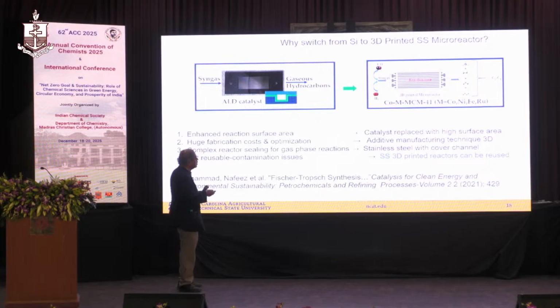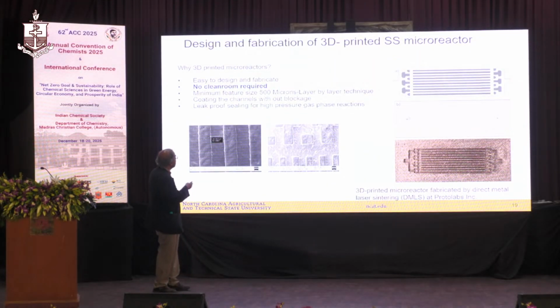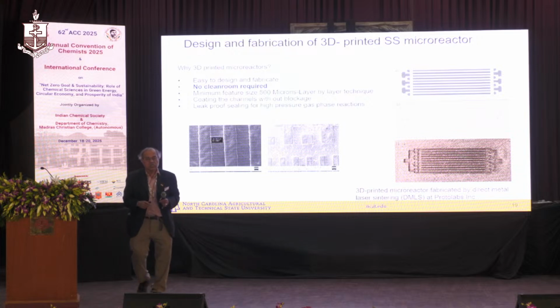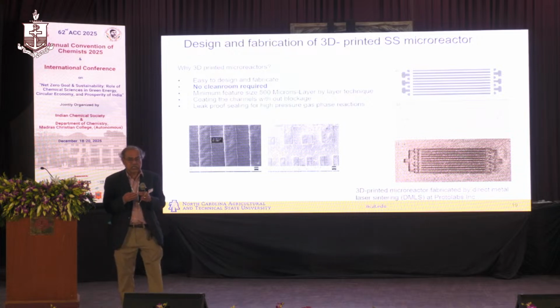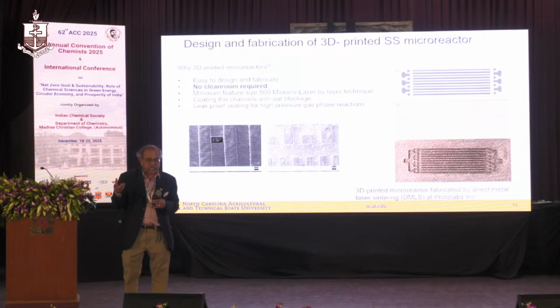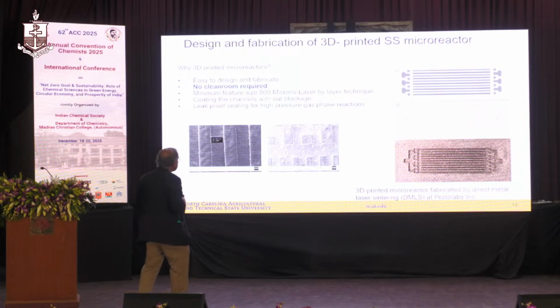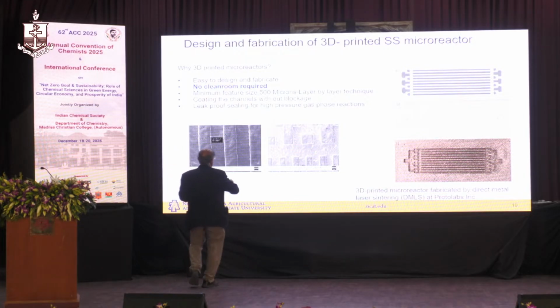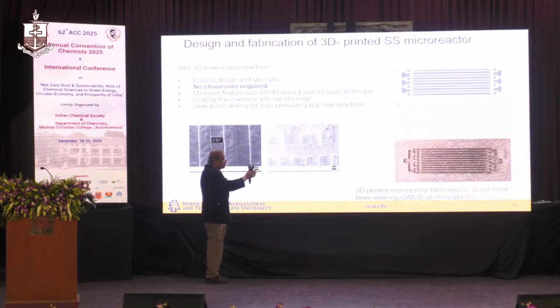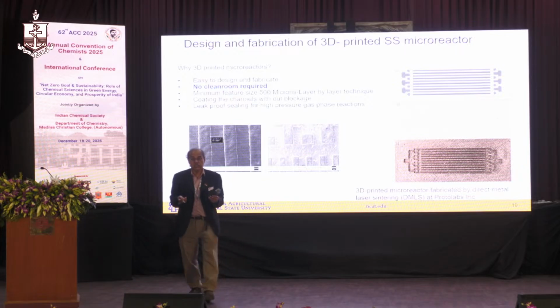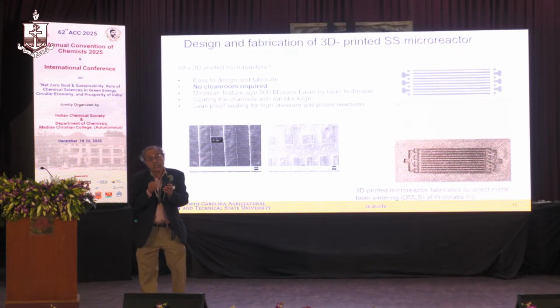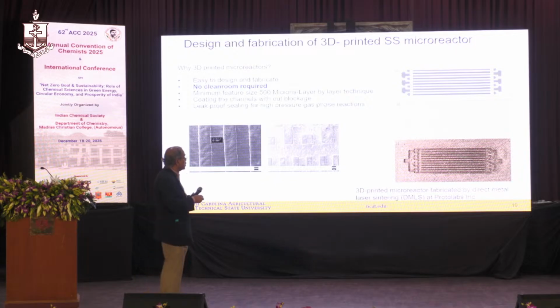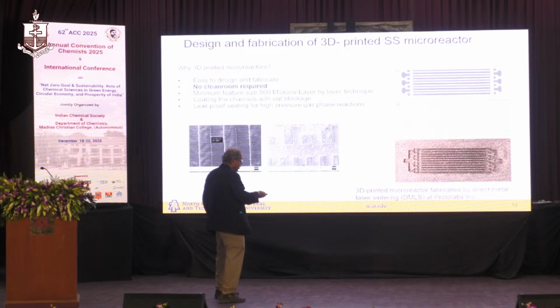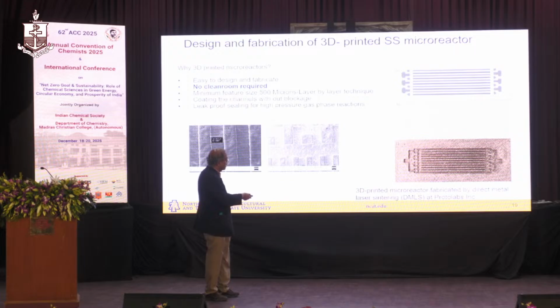this. And if I move a little bit faster, you see that no clean room is required. So you basically can just assemble this, the 3D printing by stainless steel, and then you put this, and this is how you see when you coat the channels, okay, with the sol gel and all this, and then you can put the whole thing together, and you can reuse. Previously, silicon microreactor, you can't reuse it because you seal it, applying a high voltage between silicon and glass. So here, this is Protolab, which is not very far from us,